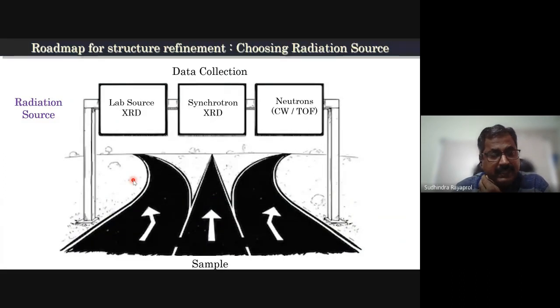So the first thing is the data collection. You can do lab source XRD, which is usually available in most of the labs. That is the most prominent one. We will all be using that, and we will be talking about this lab source XRD in the demonstrations in this lecture. But there's something called synchrotron XRD, which is also very reliable because of the wavelength and the accuracy and the resolution of the synchrotron X-rays. Another part is neutrons, which can be continuous wavelength neutrons from a reactor source, or time of flight from a spallation source. So neutrons are very important for studying magnetic structures. They can also give you information on the crystallographic structure, which is complementary to what you get from X-rays.